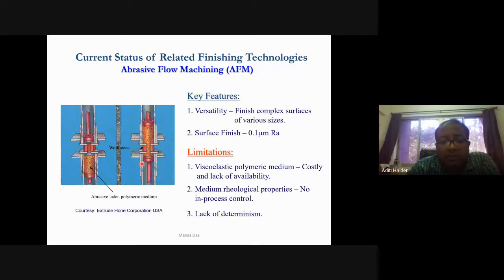So this process is very versatile. It can polish any kind of workpiece, whether internal or external. Any complex freeform surface can be polished by this process. But the only limitation of this process is that this media is very costly. This rheological media is very costly. 1 kg of this media, which is mixed with diamond abrasive particles, costs around 5 to 6 lakhs.